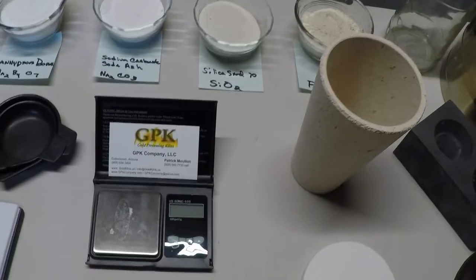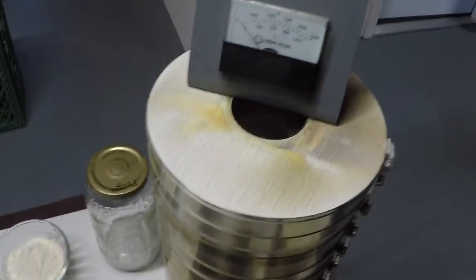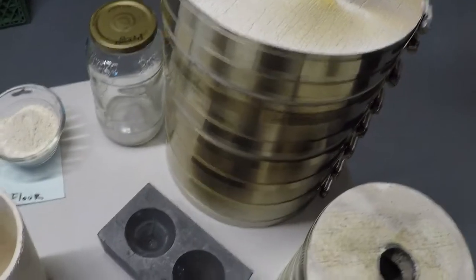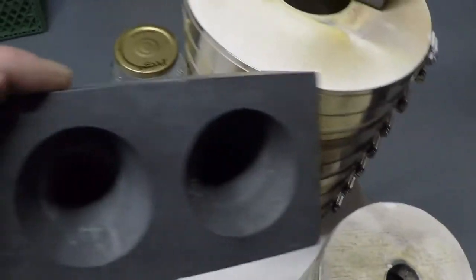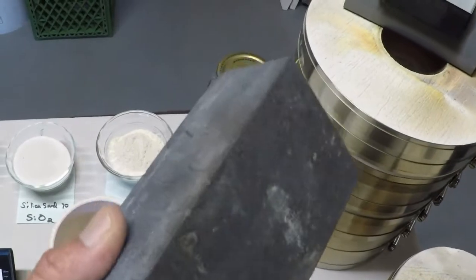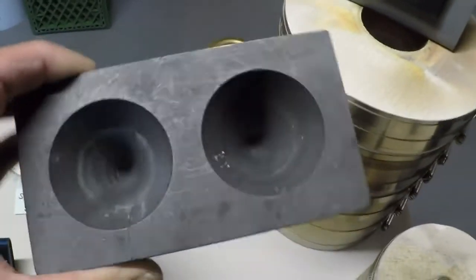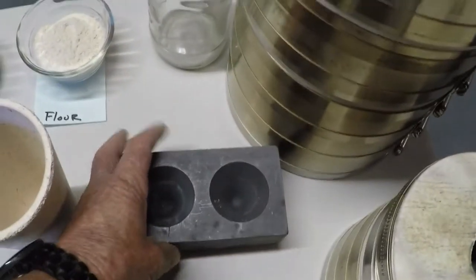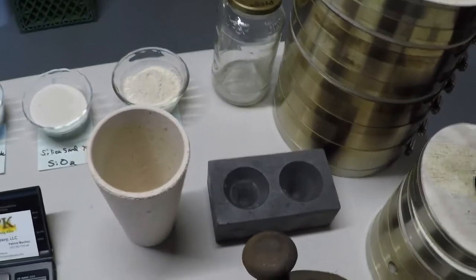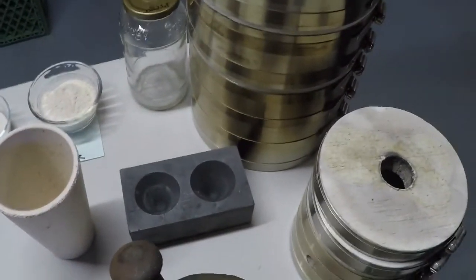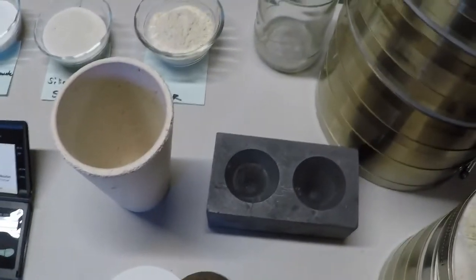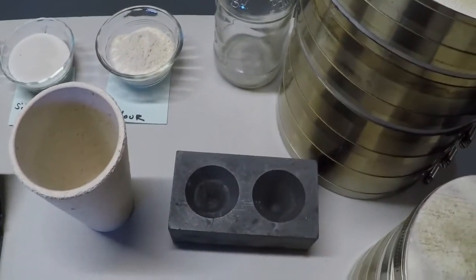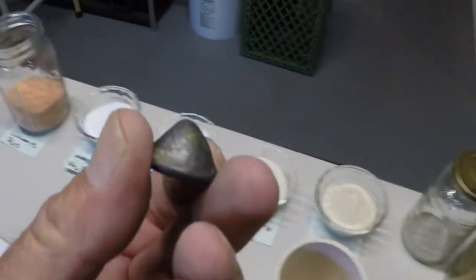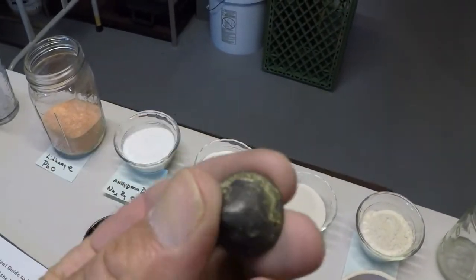And at any rate, we'll run a crucible fusion using the KK8, and then we'll pour into this conical mold here. This is a graphite double conical mold. A lot of people use cast iron, and I used cast iron for a long time, but I prefer these graphite ones. I've still got a cast iron one. I use it for a doorstop. And once we run our crucible fusion, we'll pour into there. We'll end up with a lead prill similar to this one. This one here weighs about 27-28 grams, and that's what we're going to try for.